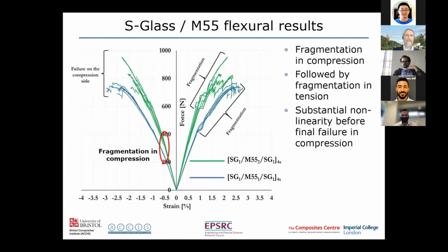So what you see here is that, first of all, we see a fragmentation in compression at about 0.5% strain, the compressive failure strain of the fibers, and you can just about see there's a bit of a change in slope. It's not very dramatic, but we do get fragmentation in compression starting here. And then later, at a slightly higher strain of about 0.8%, we get the fragmentation in tension. This is much more visible, and we get similar behavior whether we have a single or a double ply of carbon. And we get substantial nonlinearity before the final failure occurs in compression.